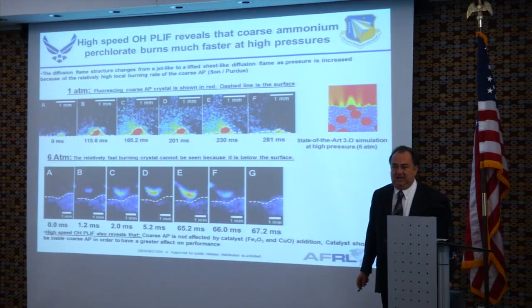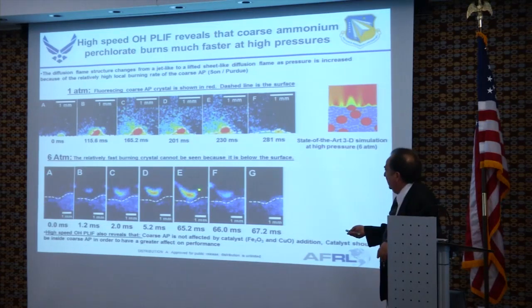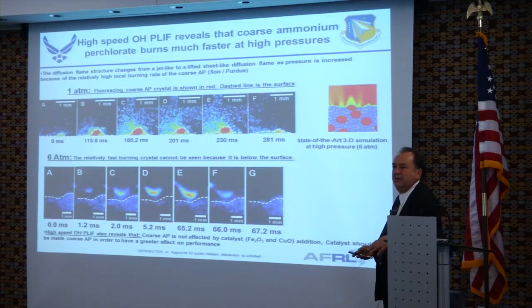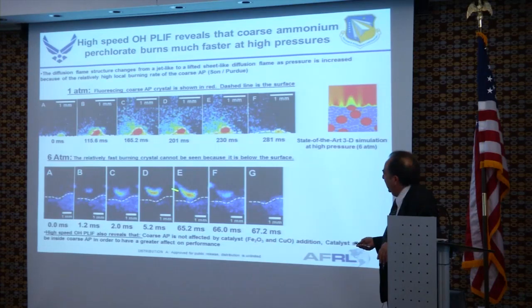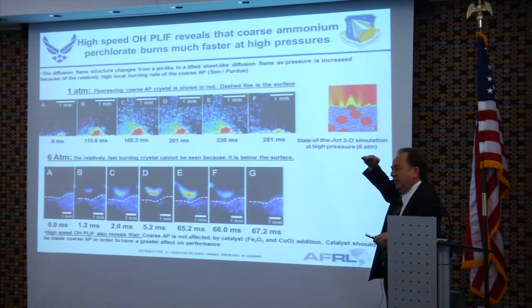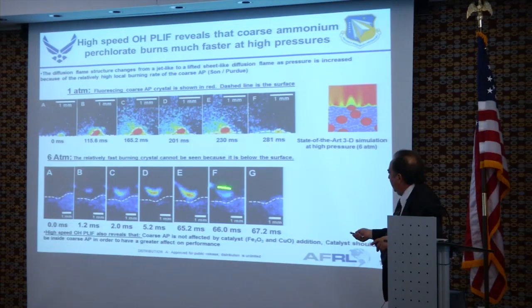state-of-the-art models today. But when they did that experiment at higher pressure, with the new available tools, because of the advancement in lasers, they realized that actually, when you increase the pressure, ammonium perchlorate burns much, much faster. In fact, it disappears from the surface. In fact, that diffusion flame becomes a lifted, inverted type of flame, which has to be put in the simulation